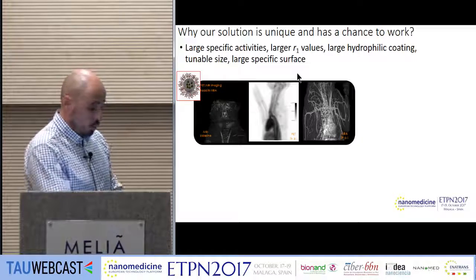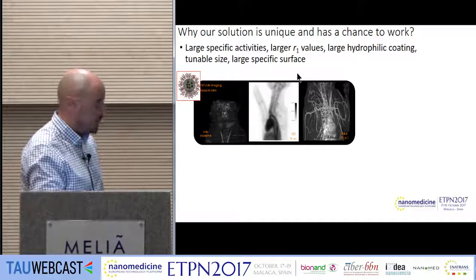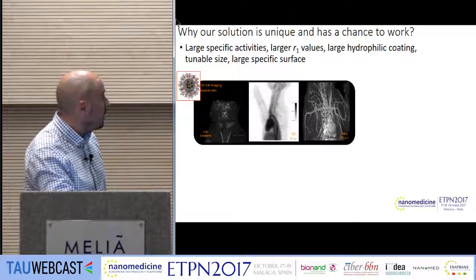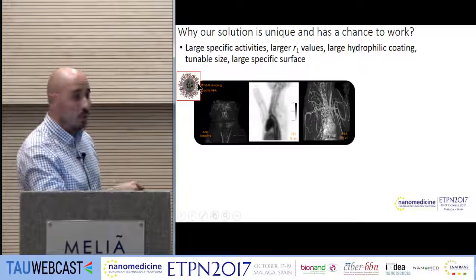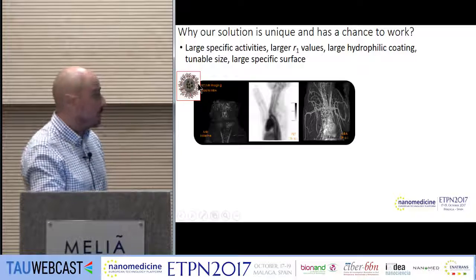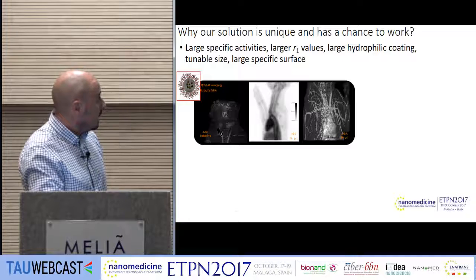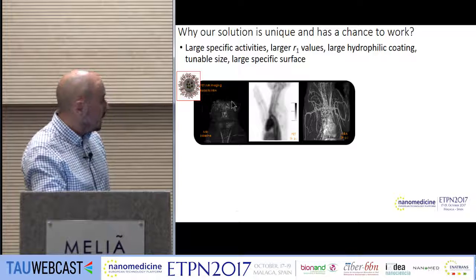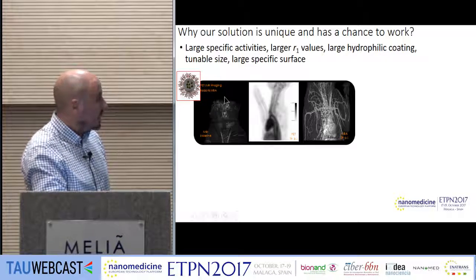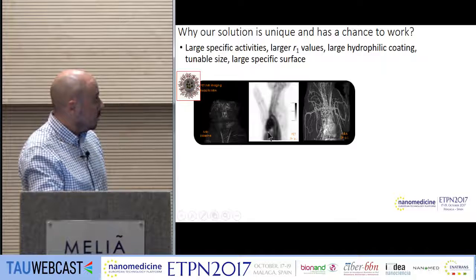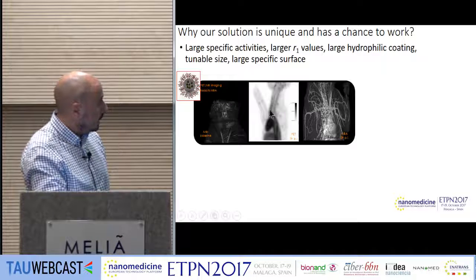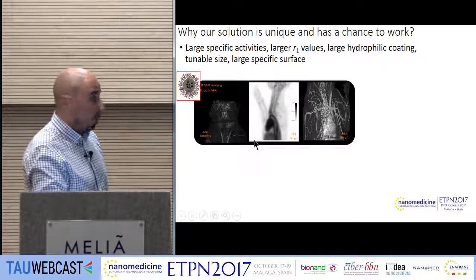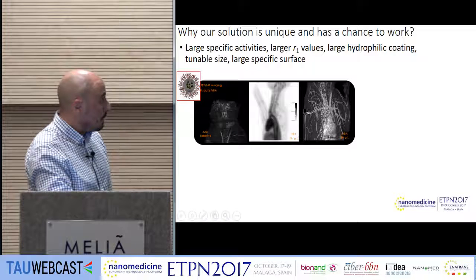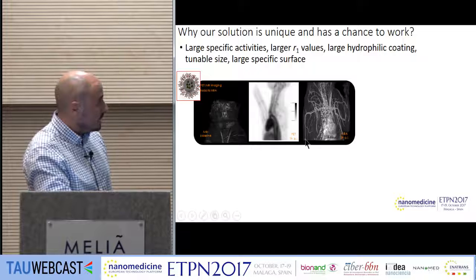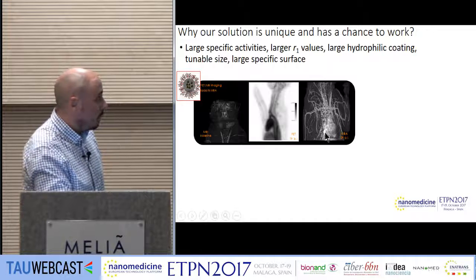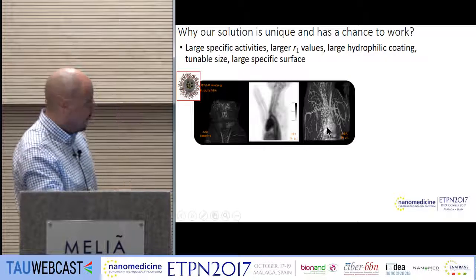First of all, if you have the nanoparticles just with the coating without any particular functionalization, because they are so small, they circulate for quite long in circulation. This is in a rabbit. This is the baseline magnetic resonance angiography. Once you inject the nanoparticles, you have the PET signal. You can clearly see the heart, the aorta, carotids. And once the radioisotope has decayed, you can take the same animal to MRI, and you can see a nice angiography of the animal, with even the smallest vessels visible.